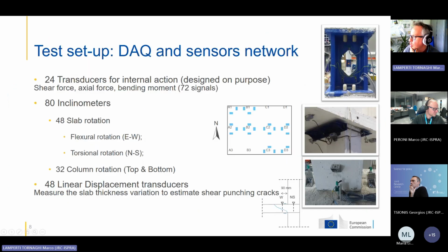Here you have a closer look at these load cells, which were designed on purpose. The location of inclinometers on the slab and on the column, and the vertical displacement transducers to measure the crack within the slab, because as you know, the crack is inclined within the slab, starting from the bottom part of the column and propagating in this way. Using this vertical transducer within the slab, we were also able to measure the cracking of this part.